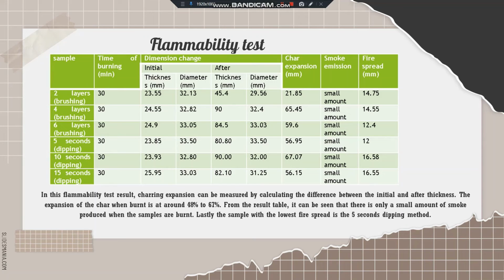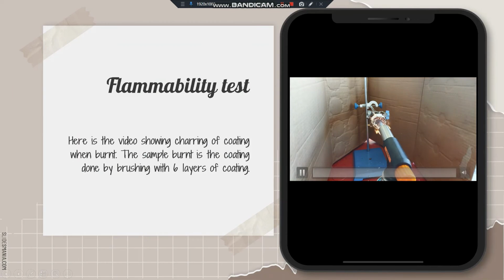Flammability tests. In this flammability test result, charring expansion can be measured by calculating the difference between the initial and after thickness. The expansion of the char when burned is at around 48% to 67%. From the result table, it can be seen that there is only a small amount of smoke produced when the samples are burned. Lastly, the sample with the lowest fire spread is the 5-second dipping method. This is one of the flammability tests that has been done, and this video shows the charring of the coating when it is burned.